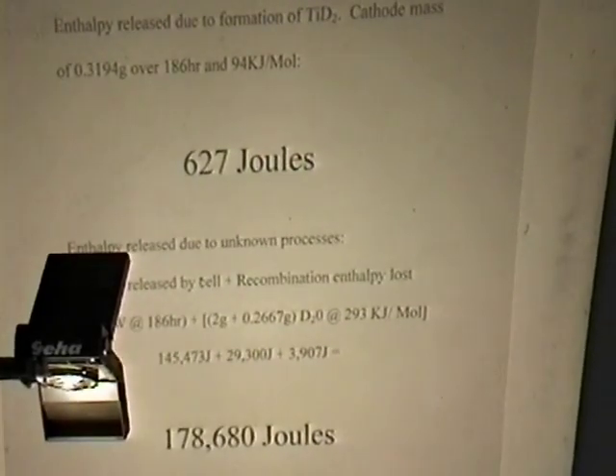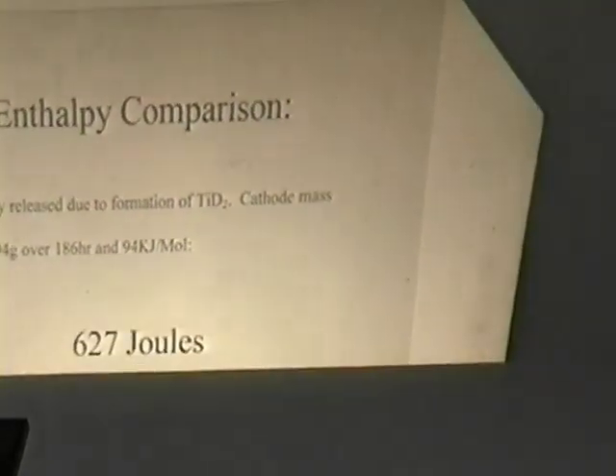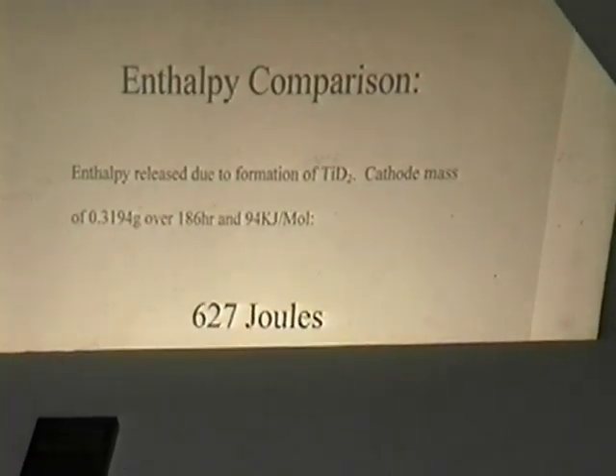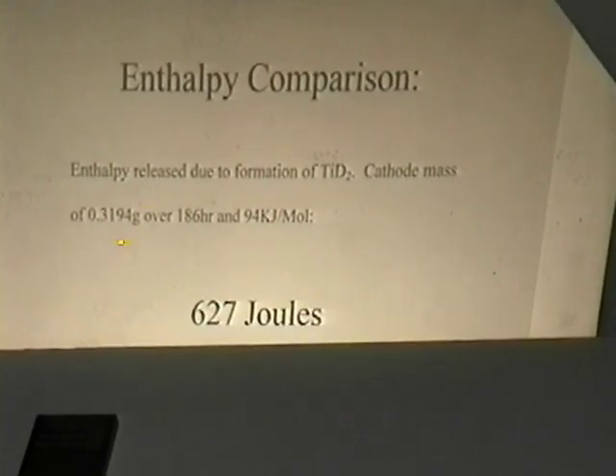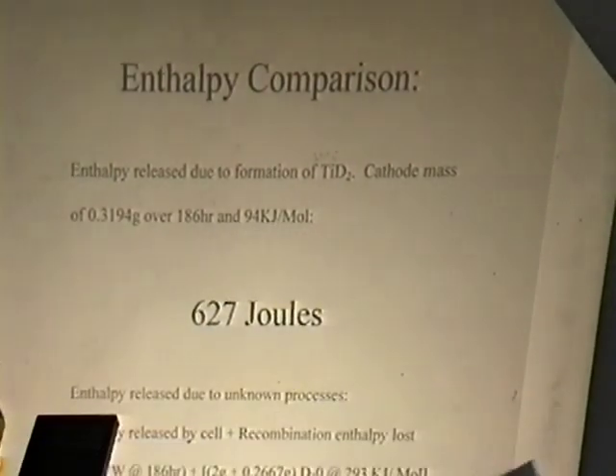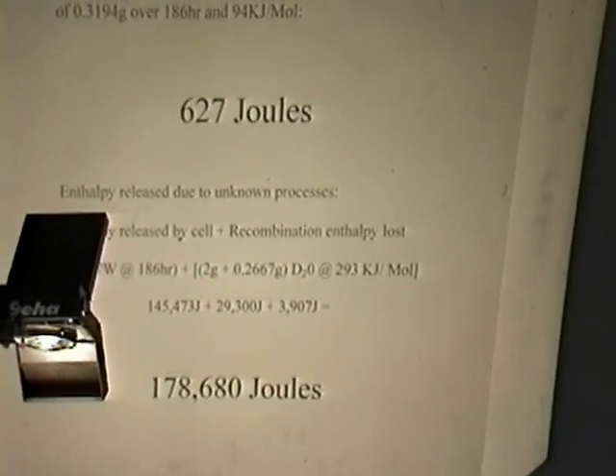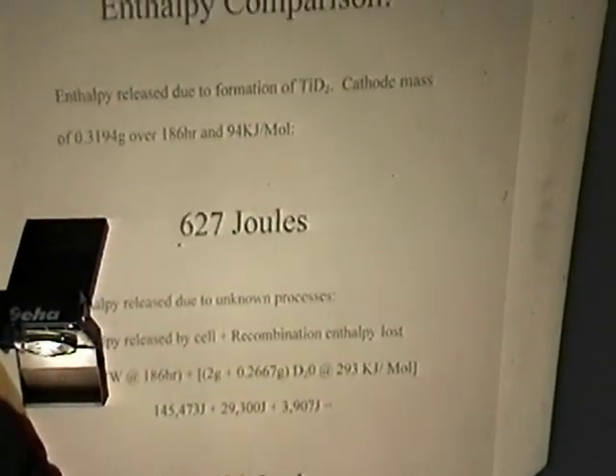Another way of looking at this is enthalpy released during the experiment. This is based on an SEC experiment. Now, the enthalpy released during the formation of titanium deuteride for this cathode mass here is about 627 joules. I say about, I read it off. If you take the total enthalpy released during the entire experiment, we find 179,000 joules. It's several orders of magnitude greater than the formation of titanium deuteride, which is the only thing you would expect to be giving off enthalpy in a cell. So that's a pretty large discrepancy there. So there's got to be something going on.